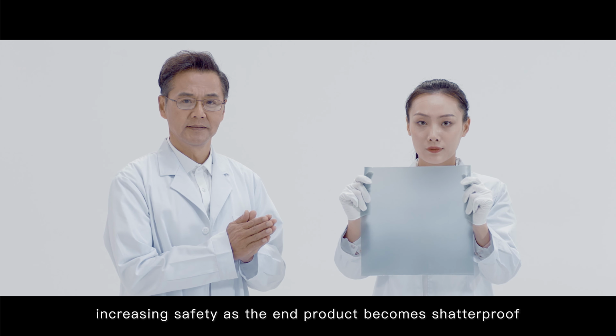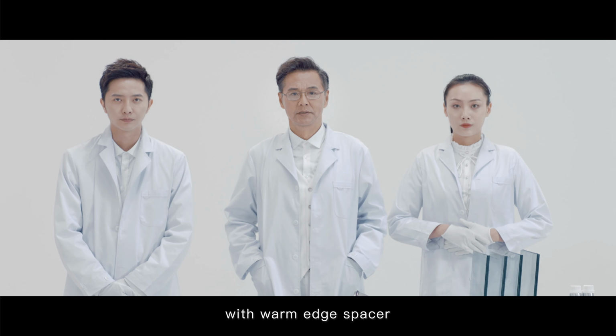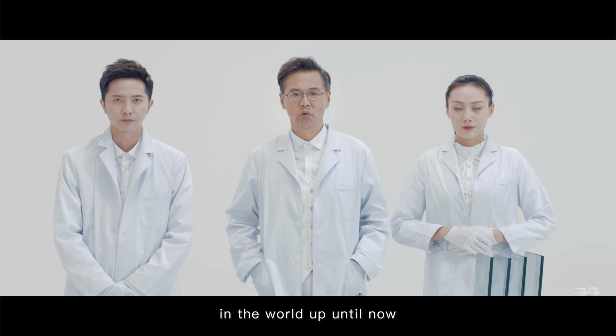with this film. This is double silver low-E insulating glass with warm edge spacer. It is one of the best insulating glass in the world up till now. Let's do a comparative test. Under the same conditions, we put the double silver low-E hollow glass in front of the infrared lamp. The infrared calorific value is 3,417. Obviously, the double silver low-E hollow glass has excellent performance with a heat barrier effect of about 60%. Let's look at the UV barrier rate. Also very good, with a barrier rate of 50%.